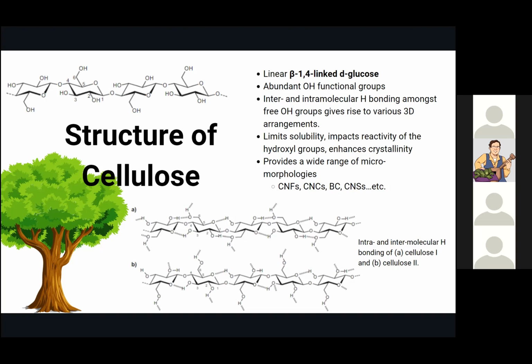Intramolecular bonding occurs principally between C3 hydroxyl groups and the other free hydroxyl groups, C2 and C6. And together with glycosidic linkages, these influence cellulose rigidity and the tendency of cellulose to crystallize or form fibrillar structures. There are many forms of cellulose depending on the state of intermolecular bonds, two of which are pictured in the lower picture here. So cellulose 1, or native cellulose, is the top one. It's A.